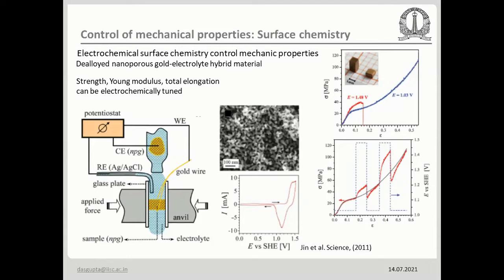So now, if we take this nanoporous gold sponge and put it in a different electrolyte, electrochemical oxidation is possible even for gold. So we can have a very thin monolayer of surface oxide. But since it's nanoporous, the surface area is so high, that even if you have 1-2 monolayers of surface oxide, you can change the mechanical property by a huge extent. So that has been shown.